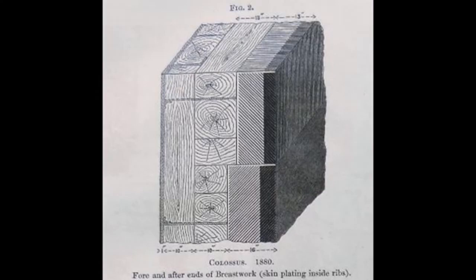However, early attempts to replicate the wood-iron combination by simply bolting a steel face onto an iron plate didn't work very well, with in some cases the steel actually being a detriment, as fragments of shattered steel plate were forced back into the iron, spreading it apart and making it easier for the shell to force its way through in a manner similar to World War II-era armour-piercing shells with their armour-piercing caps. Additionally, once they were broken, shattered shards of armour steel would fall away, exposing the now much thinner iron plate to relatively easy penetration by follow-up shots.